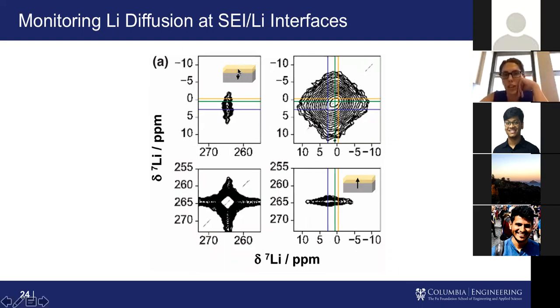We also get directionality from this experiment. So this cross peak indicates lithium ions that are moving from the SEI to lithium metal. This one indicates lithium ions that are moving from lithium metal to the SEI. And then actually we can zoom in even further and take a look at this blob and see, how is lithium oxide exchanging with lithium fluoride by zooming in on this region, for example. And we can start to pinpoint all of these different diffusion coefficients over these individual interfaces.